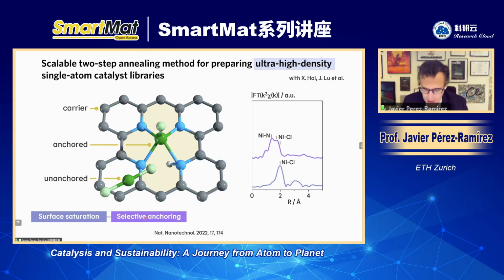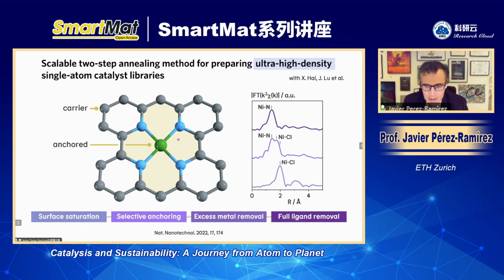What we do after this selective anchoring is a metal removal, where we remove by simple washing in water the excess of precursor that has not been anchored because there are not sufficient anchoring sites. And upon removing this excess metal, it's no problem whatsoever to do a high temperature calcination to remove all the chlorine from the nickel, forming only nickel-nitrogen bonding because that nickel was already anchored. So that's a little bit how the system works. That's why it's two-step: this is the first annealing step and the second annealing or high temperature treatment step. And in between, you have to remove the excess metal, which you can, of course, recycle for an upcoming preparation.